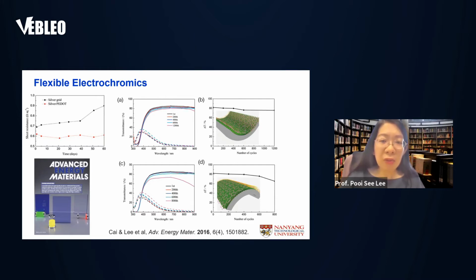Here shows the many thousands of cycles in optical modulation in terms of transmittance over a range of 80% transparency down to less than 5% blocking of light, indicating that this film can be electroactive controllable in tailoring the amount of light that is transmitting through the transparent layer. And therefore, it can be mounted onto transparent glass or plastic substrate when required.